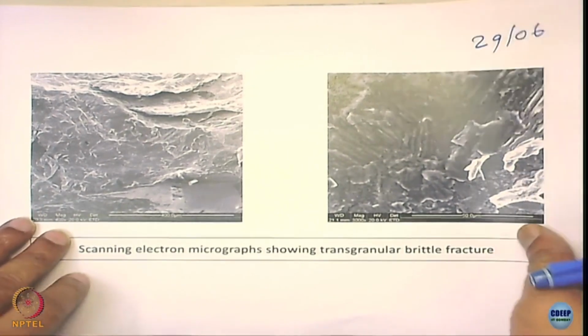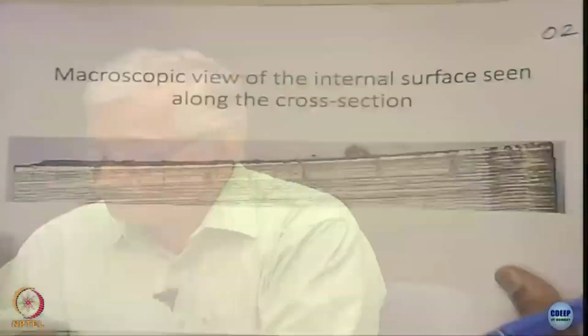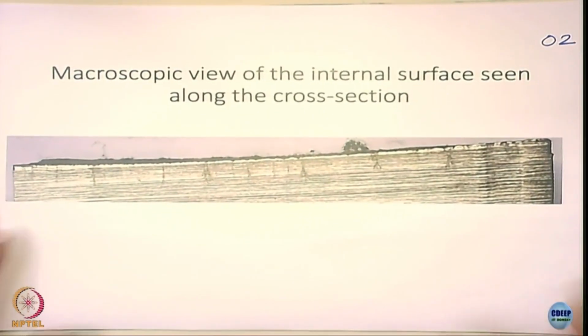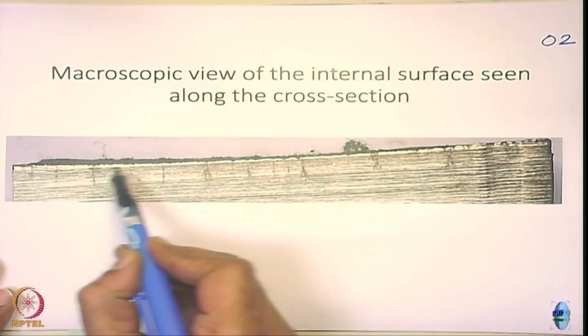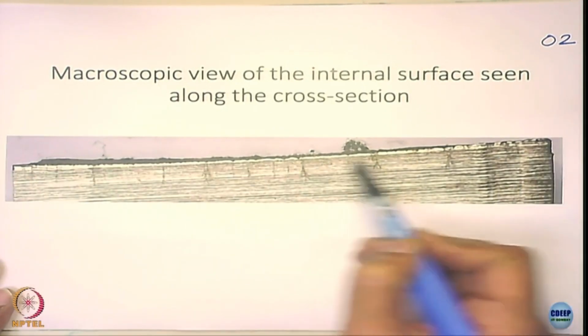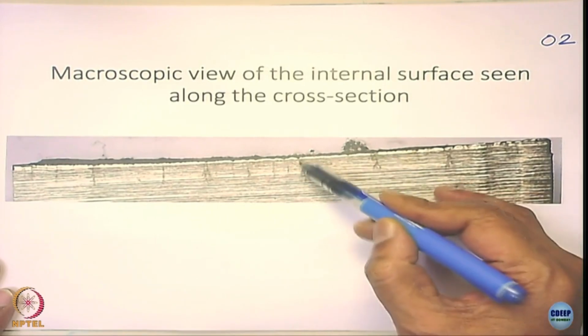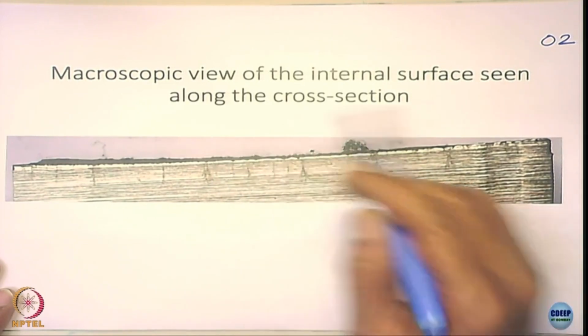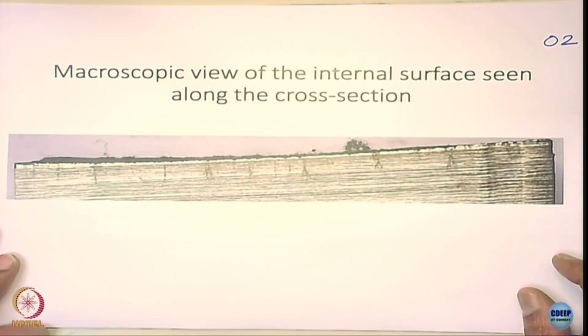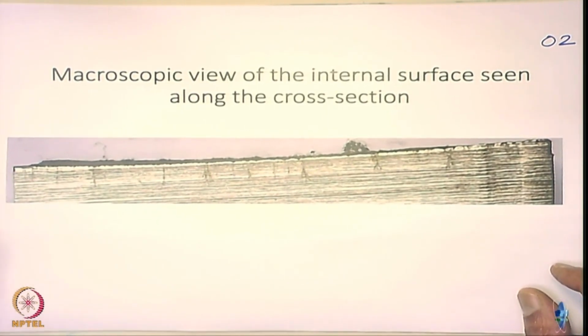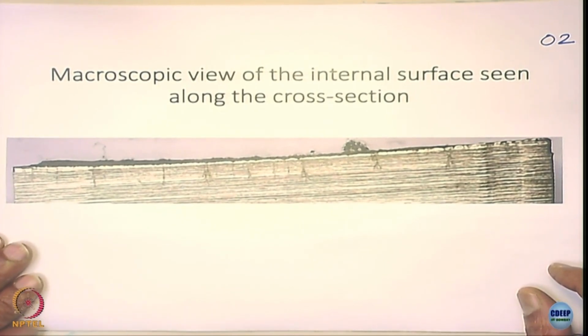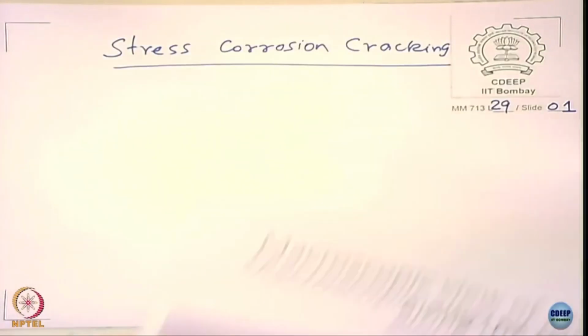Okay, so the problem in stress corrosion cracking is that it can cause a premature failure, and yet it is not going to cause too much corrosion. See here now the surface. This is the surface internally, and you do not really see much corrosion at all. I hope you were able to see this clearly. Wherever there is a crack, and in the subsequent places, you are not seeing any corrosion. So visually they are not undergoing severe uniform corrosion at all, and so this corrosion is very localized and is called stress corrosion cracking.